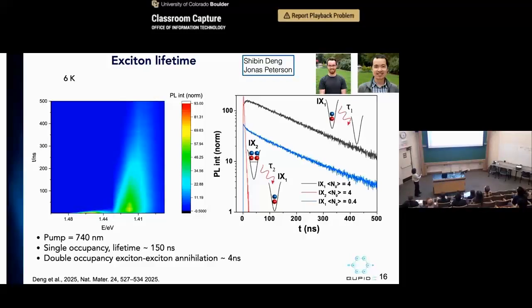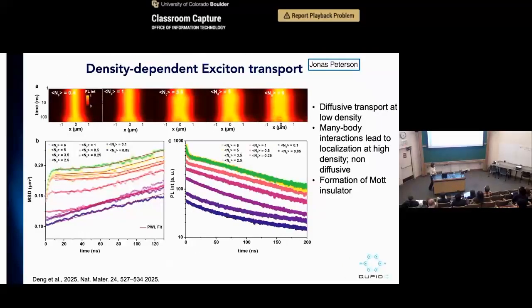And if we look at the higher energy peak that comes from the double occupancy of these Moiré sites, the lifetime is much, much faster, about a few nanoseconds. And this is coming from the fact that if you have two excitons on the same site, they also undergo this exciton-exciton annihilation, and this is much faster. So we can also dynamically separate these two types of situations.